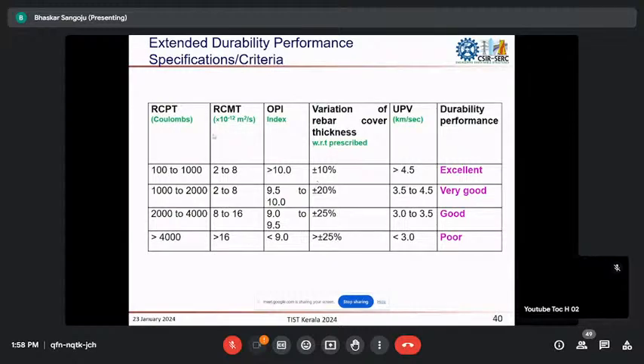bad appearance. So there you may have to go for a fully non-destructive test where you can use the cover thickness as one of the parameters and ultrasonic pulse velocity as one of the parameters. And rebound hammer also can be used, but if you want to ensure the quality and integrity of concrete, it is better to use this UPV test. And here in these RC box units, we followed this type of classification. If the variability in cover thickness is plus minus 10%, then we say the durability performance is excellent. And if it is plus minus 20, it is very good, and if it is plus minus 25 it is good. If it is greater than plus minus 25, then we say the quality of construction is poor.